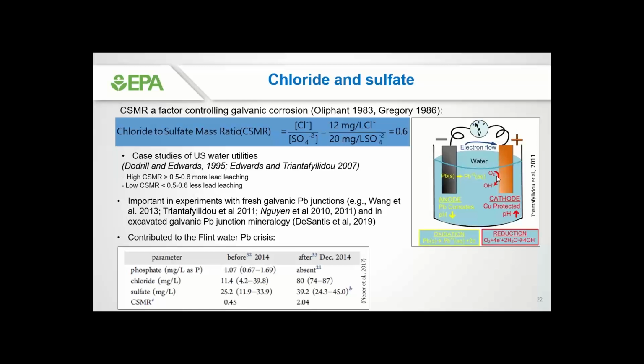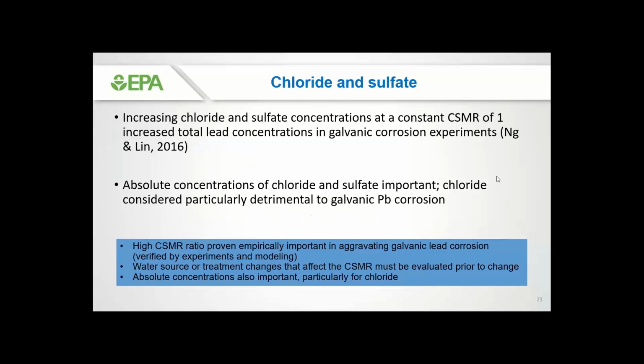Yes, absolutely. So talking about chloride, thanks, Tom. Talking a little bit about chloride and sulfate, you may have heard this term, chloride to sulfate mass ratio. It's basically the fraction of chloride divided by sulfate. It's been empirically shown to be important. The higher the chloride to sulfate mass ratio, the higher the lead leaching. An example was Flint, where the table at the bottom shows that when water quality changed, the chloride to sulfate mass ratio moved from about 0.5 to about 2, which was one contributing factor to water quality problems and lead leaching there. The CSMR is an important ratio empirically in aggravating lead leaching, especially galvanic corrosion.